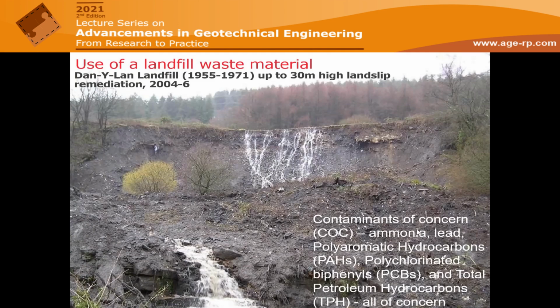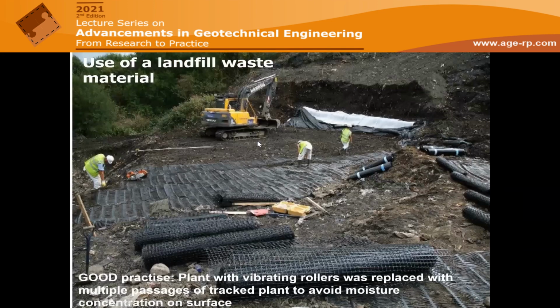They were very highly contaminated: ammonia, VOCs, PAH, petroleum hydrocarbons. But again, no problem at all, because the high density polyethylene geogrids are chemically inert. And the lesson we learned from this one was that because we didn't know how this material would react in compaction, we started with vibrating rollers, but then we found out that the water was ponding on the top. So they replaced the vibrating rollers with just passes of tracked plant, and that sorted the problem of moisture concentration.